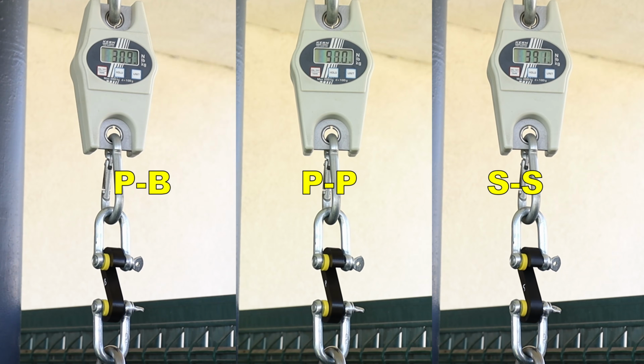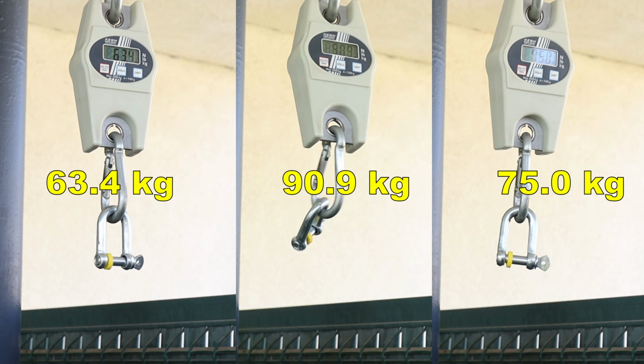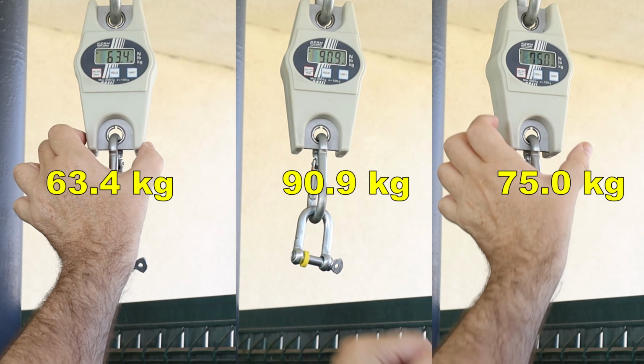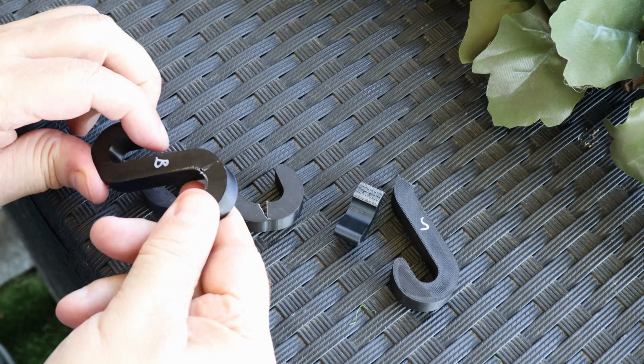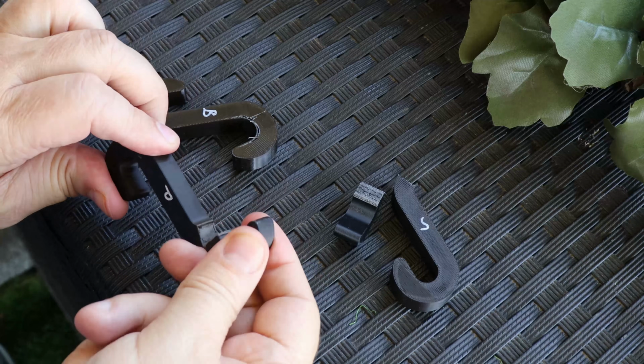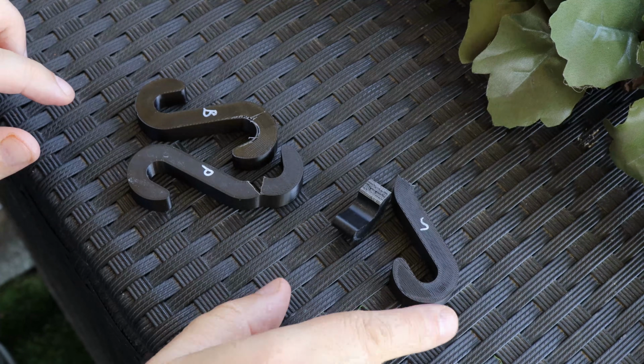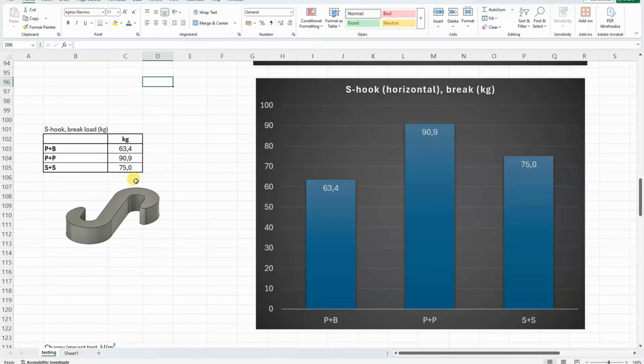Hooks printed in horizontal position. Polymaker PC-ABS still connected with both objects. Stratasys break was more rigid. So these hooks are printed in horizontal position, and we can clearly see the advantage of the normal extrusion compared to the underextrusion. Polymaker parts printed on Prusa are the strongest, and the Stratasys is somewhere between.